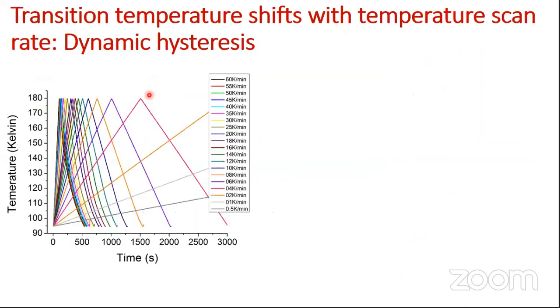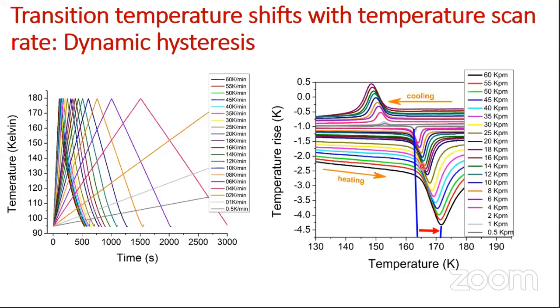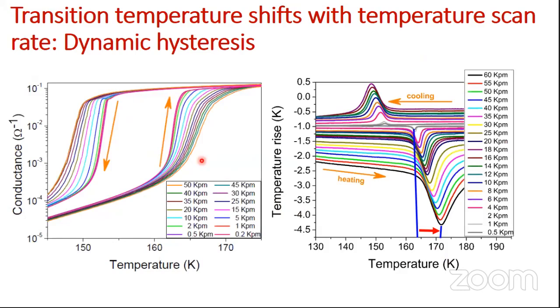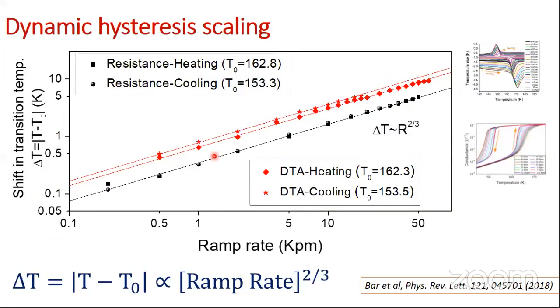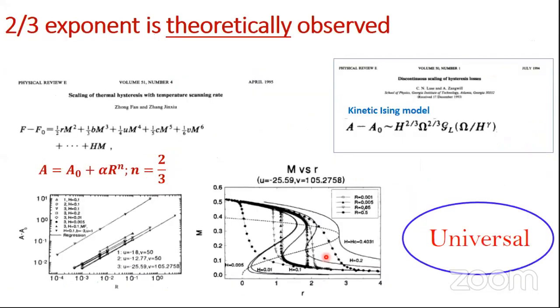So if we increase the ramp rate from 0.5 Kelvin to 60 Kelvin per minute, I get that this transition temperature is shifted. And we did the resistance measurement, and this area of the hysteresis is also shifted with this rate of change of temperature. So this shift in transition temperature follows a scaling relationship with this ramp rate, and this exponent 2/3 is the mean field exponent of spinodal transition. So 2/3 is at least universal in its mean field concept.